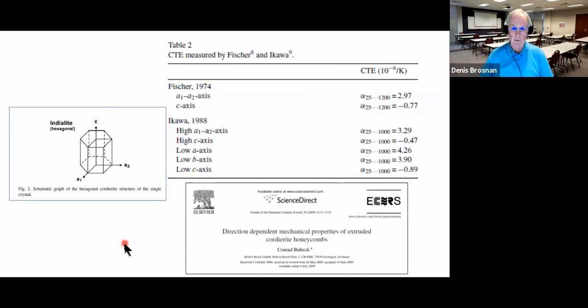So what you're going to find out is that cordierite ceramics are typically extruded, and with plate-like kaolin crystals, the cordierite is going to grow on the kaolinite relics as you heat them. If you orient enough kaolinite particles in extrusion, which is easy to do because they're flat plates and they like to align in the direction of extrusion, then you can get a very low thermal expansion coefficient. You can't align them all because these are pretty quick extrusion processes, but if you align most of them, you'll be able to get the thermal expansion coefficient pretty low. So that's the central idea: manufacture in such a way that we can get a low thermal expansion coefficient.